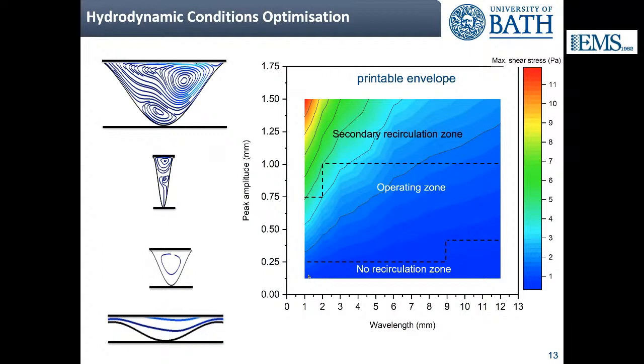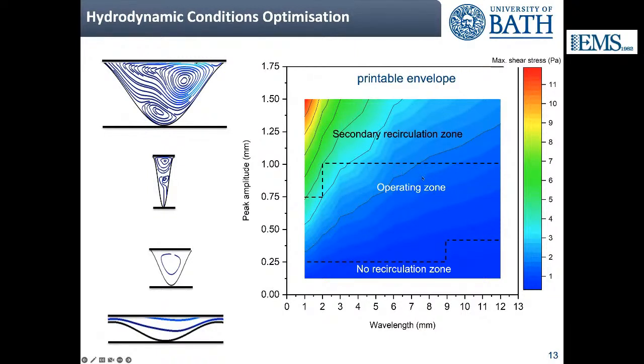However, if you look at CFD, if you are in this area where you have these very pointy peaks or troughs, which is represented by the second CFD plot on the left, you have lots of secondary recirculation zones. So in fact, rather than minimizing fouling, you're actually increasing fouling. So all this area here at the top cannot really be used because it defeats the purpose of minimizing fouling. If you go at the bottom, where you have very shallow peaks and troughs, there's really no turbulence happening. And so again, it's like if you had a flat membrane. So in practice, the area where you want to operate is this operating zone in this area here.